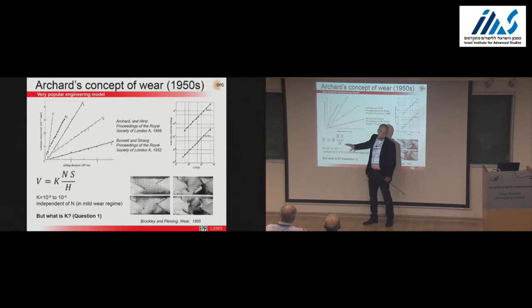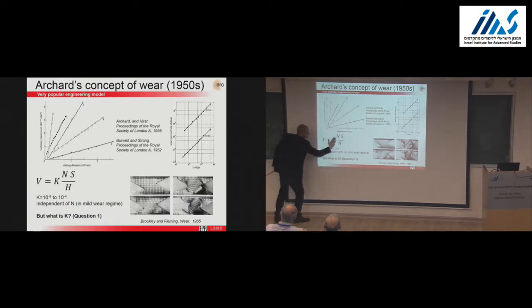So we'll come back to this. There are actually simple theoretical arguments you can use to come up with this. So that's a theory, that's a measurement. Forget about this. So you would like to have this perfect equality, but it doesn't work. So when it doesn't work, you have this magic factor called the K factor that you throw in the equation. And K is not a small adjustment. It's not a 10% adjustment. It is more like a 6th order of magnitude adjustment. So K is a small number, 10 to the minus 8 to 10 to the minus 4,